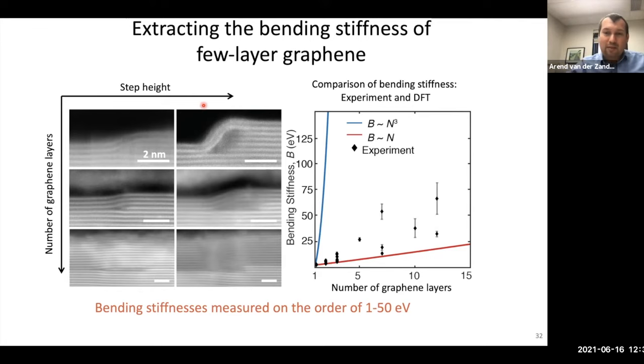And what we found, so here on the right is a plot of this bending stiffness versus the number of graphene layers. All those black points are the measured values. There are two models built on here. The blue line is what you would expect from classical continuum mechanics. The red line is a model where you would expect that the layers do not interact at all.